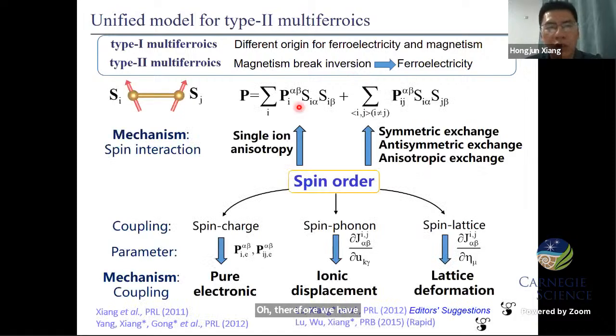However, for type 2 multiferroics, the ferroelectricity is directly caused by the magnetism. So this magnetic order breaks the inversion symmetry. This is easy to understand from the symmetry argument, but the microscopic mechanism of this magnetic order induced ferroelectricity is not easy to understand. Therefore, we proposed the unified model for type 2 multiferroics in recent years.